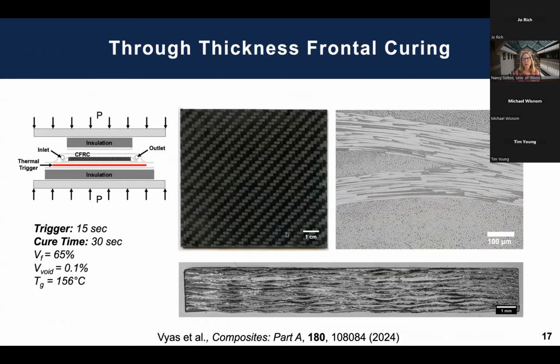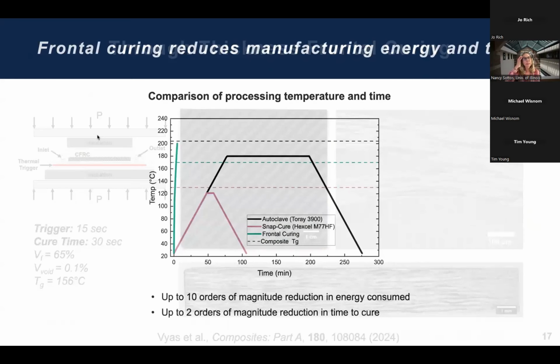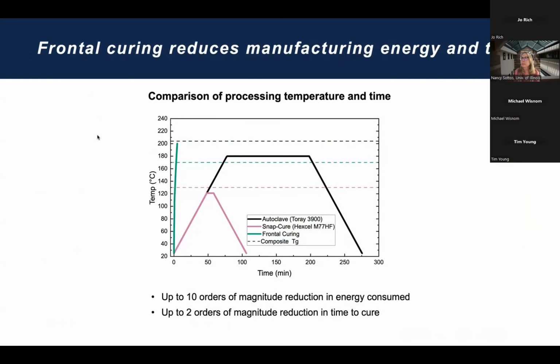The triggers are on for seconds to minutes. And we can get high volume fraction, 65% volume fraction. So it's a very fast way of making a nice composite without an autoclave. The key to getting the volume fraction up is to add some compaction, as you see in the image there. And just as comparison, basically we look at frontal curing is the green curve here.